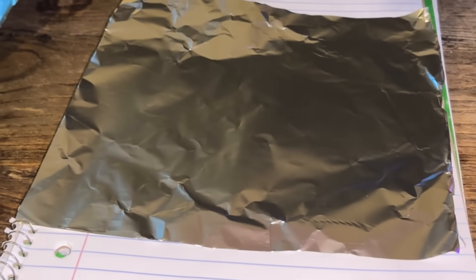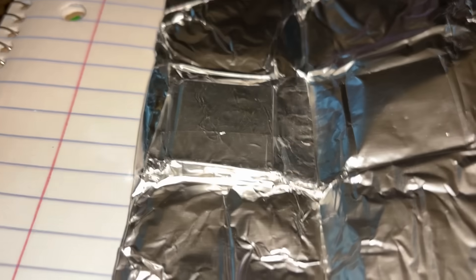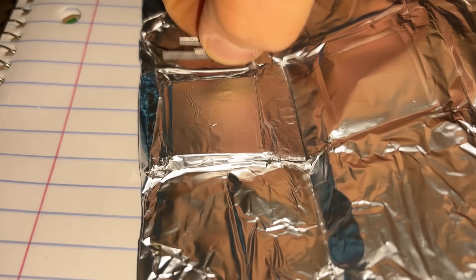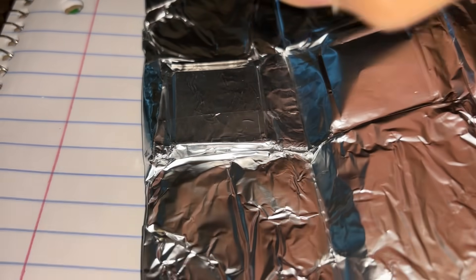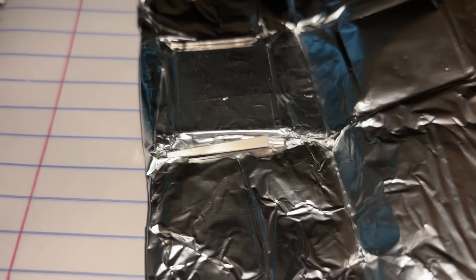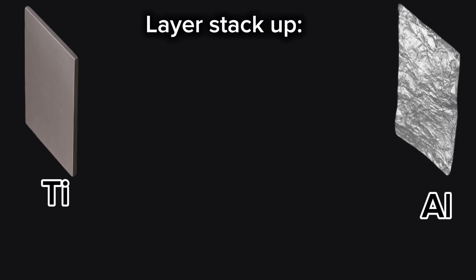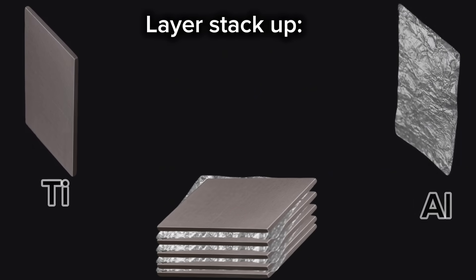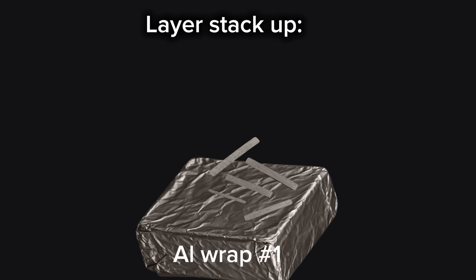This would hopefully isolate the atmosphere just a little bit and reduce the amount of oxygen that makes it in. Once I had that wrapped, I repeated that process and wrapped it again in another layer of aluminum foil. However, within this layer, I included some small chips of scrap titanium. The aim is that these little chips of titanium serve as sacrificial pieces to attract the oxygen and form detrimental phases on themselves rather than the part that I'm actually interested in.